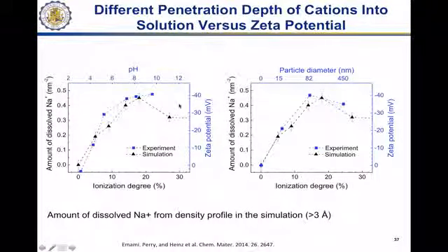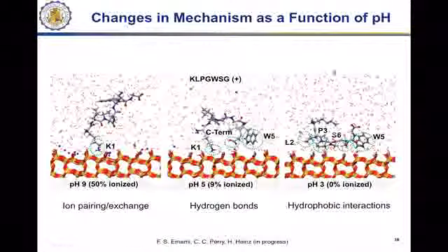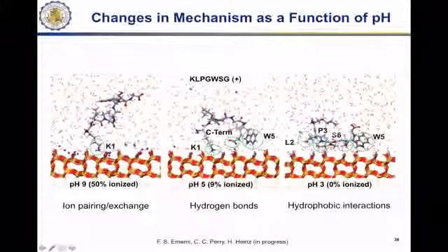Those correlations are really good, both as a function of pH and as a function of particle size. For the larger particles, we have a mixture of Q2 and Q3 environments, medium size is more Q3 environments, and smaller particles have a little bit less ionization. But those trends are really interesting, and they allow quantitative comparisons to measurements.